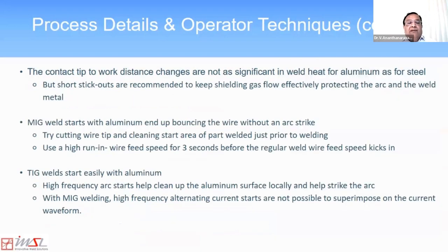And if your MIG welds with aluminum end up bouncing the wire without an arc strike, try cutting the wire tip and cleaning the start of the area. And this was found to be very necessary when we were welding aluminum door panels in an automotive application. We didn't have to cut the wire tip there. The aluminum arc welding power supplies have a way of finishing the previous weld while leaving the tip of the wire very sharp.